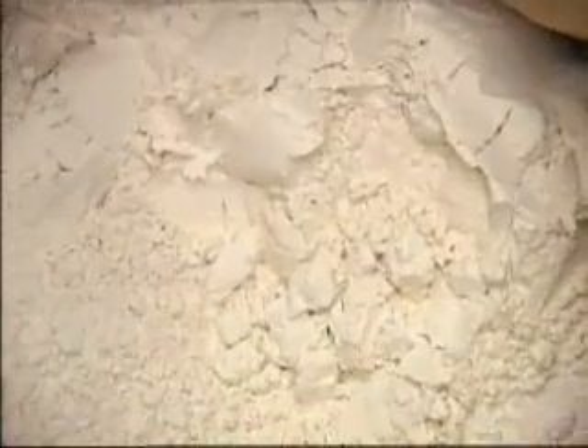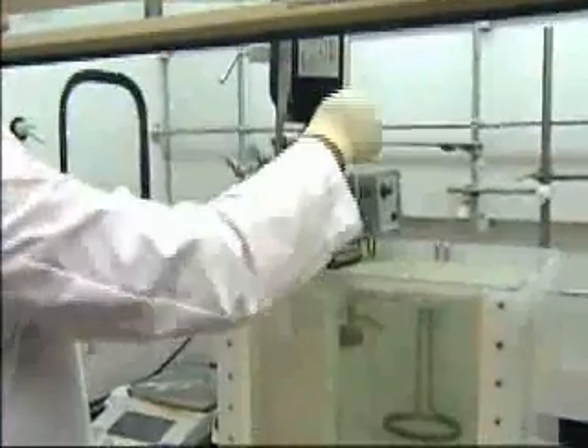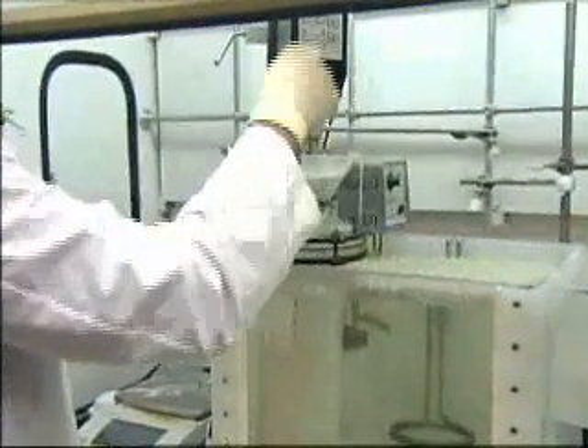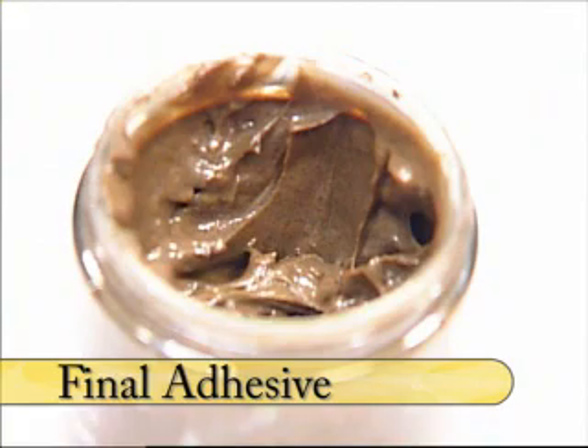Commercial particle boards are synthesized using urea formaldehyde resins, and these slowly liberate formaldehyde over their lifetime. The Thames-Rawlins research group has synthesized formaldehyde-free particle boards using soybean protein-based adhesive. Soybean protein is dispersed in water, thoroughly blended with appropriate additives to form the adhesive.